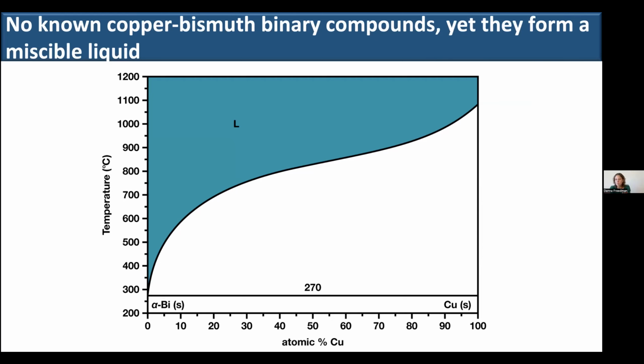So one of the first systems that we went after, and this is terrible, I would tell my students not to give a talk this way, but the truth is one of the first systems that we went after looking for high pressure binaries was the copper bismuth system. And we went after this system for two reasons. One is right here we have this nice phase diagram where we're looking at the atomic percent of copper versus bismuth and temperature. And here we see that we have this liquid region where copper and bismuth mix like water and ethanol. And so because of this mixing region, we hypothesized that we could use relatively low pressures to access a copper bismuth binary compound.